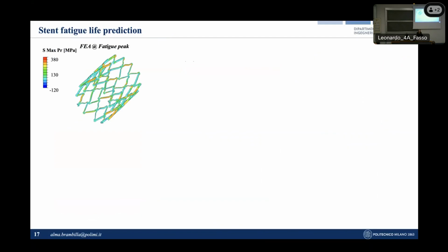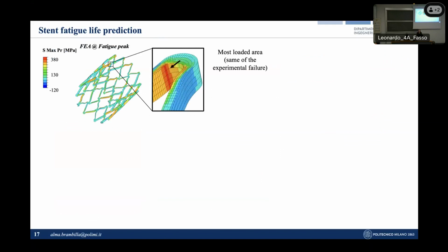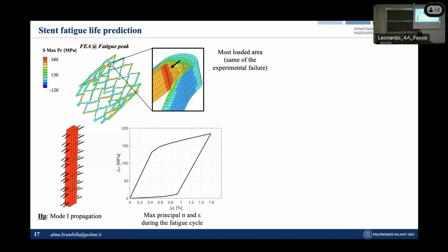In this case, the tests were supported by finite element simulations, given the complex loading condition of the stents, in order to be able to evaluate the local response of the material in the most critical region in terms of maximum principal stress and strain. So, in particular, 15 elements in the most loaded area were considered. Mode 1 propagation of the crack was assumed, so an opening of the crack along the thickness in the direction perpendicular to the maximum principal stress, which is here depicted. And for each one of these elements, the stress-strain cycle was computed. So, exactly the same procedure that I described before.